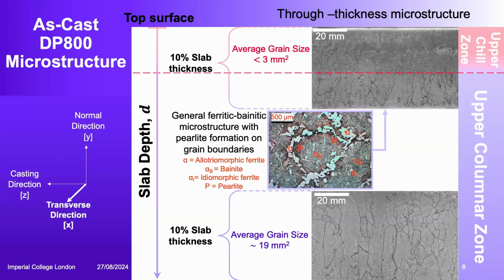You can see in the bottom image here, they are aligned with an axis down into the page. Another takeaway from this is that the microstructure of as-cast DP800 is bainitic ferritic. This is to be expected. You can see a lot of allotriomorphic ferrite forming in the grain boundaries. But there is also pearlite forming at the grain boundaries, no doubt because the diffusion rates are higher.